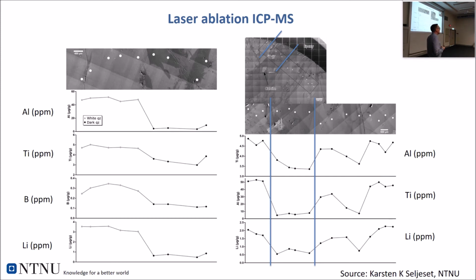This is confirmed with laser ablation ICP-MS, where, if you go back here, you see that this is still the SEM-CL picture. You see bright quartz, dark quartz, and the equivalent laser ablation analysis. You see that the content of the different elements drops when you enter into dark, late generation quartz. Same for both. This is a recent work done by one of my master students on this deposit.